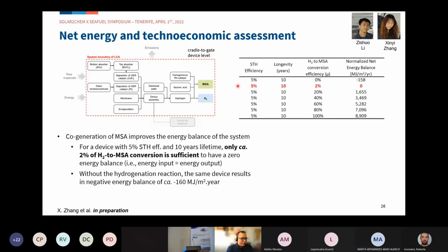The result is shown here first for the energy balance. What we show in this table is that cogeneration of MSA improves the energy balance of the system. Take an example here: a device with a solar-to-hydrogen efficiency of 5% and a longevity of 10 years. If we first consider no production of MSA, i.e. just a hydrogen production device, we actually have a negative net energy balance of about negative 160 megajoules per meter squared per year. What this means is that the energy output we produce throughout the 10 years cannot compensate for the energy input we put in to build the system.